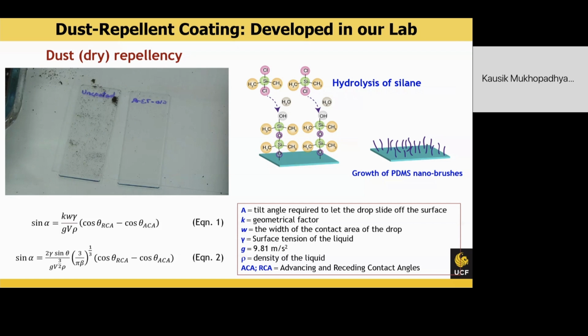One of the important aspects from that Cassie-Baxter model, or from our model, is contact angle hysteresis, which has a very significant physical meaning, because it is directly linked to the lateral adhesion as well as the tilt angle. And this tilt angle is the determining factor, based on a drop shape model, of how fast a particle sitting on top is going to slide. That's exactly what we are taking care of. Although, as I said, it's very preliminary data, we have gotten to a point where we are confident enough that this can move forward with even simulants.